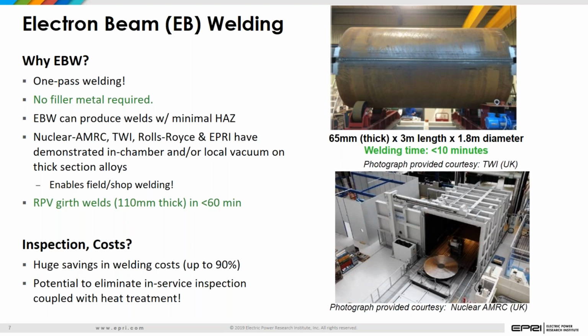Specifically, why are we looking at electron beam welding? Electron beam welding is a one-pass methodology. So instead of requiring dozens of passes to produce a weld, you can actually produce it in one pass. There is no filler material required. It's basically an autogenous process. So you eliminate any issues associated with embrittlement when that is actually exposed to radiation further down the road.